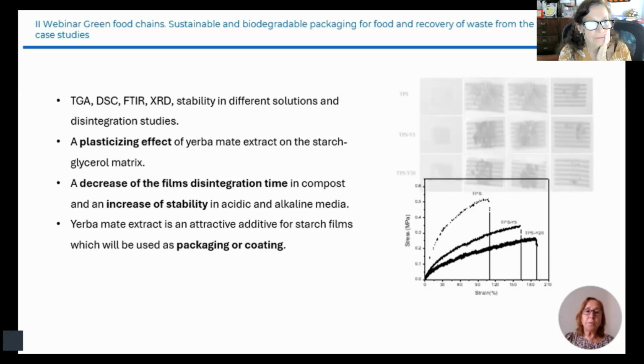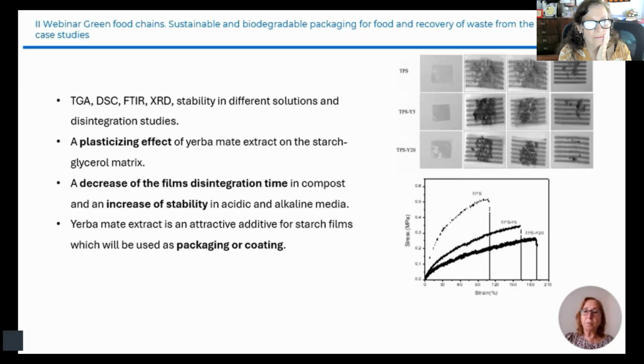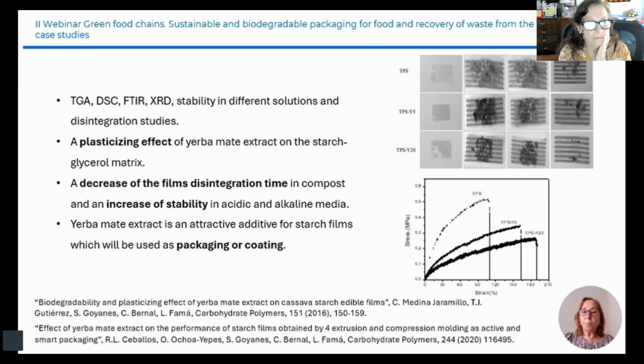We also found a decrease of the films' disintegration time in compost in laboratory conditions and an increase of stability in acidic and alkaline media. So we observed that the extract is an attractive additive for starch-based films, which can be used for packaging or coating.